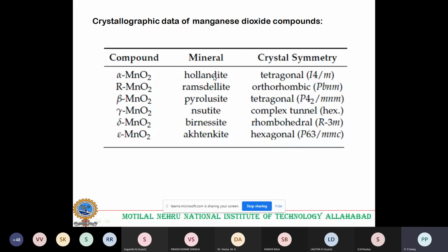This is the crystallographic data I have taken from some reference. So alpha MnO2 is the tetragonal structure, R-MnO2 is the orthorhombic. So suppose you have prepared your film and found that it is orthorhombic, then we can say that it is R-MnO2. In my case, I found the manganese oxide film is hexagonal, and we say that it is epsilon MnO2. So these are the standard data available online also.